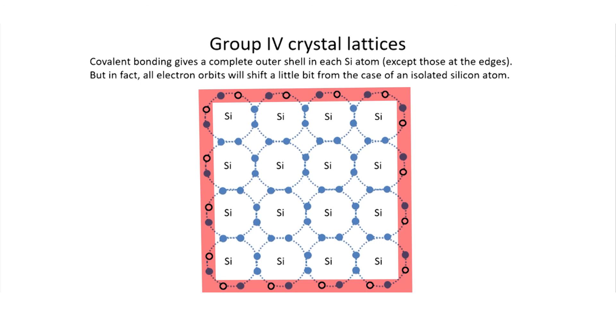There aren't any more silicon atoms at the surface, so these open states will be dangling bonds. And this is why surfaces are always different than the interiors of crystals. And it's also why the work function of a crystal is related to the electronic structure at a surface, rather than something deep inside the crystal. These dangling bonds at the surface of a crystal of silicon mean that silicon will react with its environment. These dangling bonds can react with oxygen, for example.